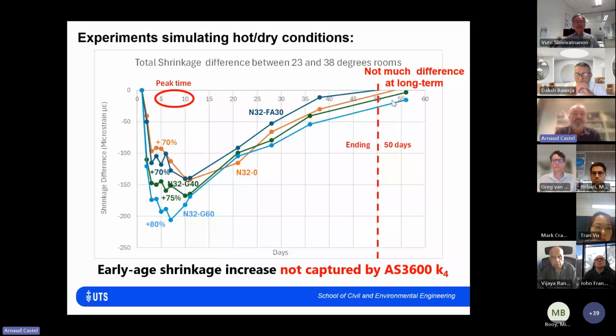Here, you can see the red dotted line, R7, so it's 7 days. And the criterion will be that a concrete that performs well should not crack before 7 days. And there's a lot of concrete that are actually not passing the test at all. Most of the concrete do not pass, just a few concrete can pass that test. I'm not here to discuss the detail of each mix design.